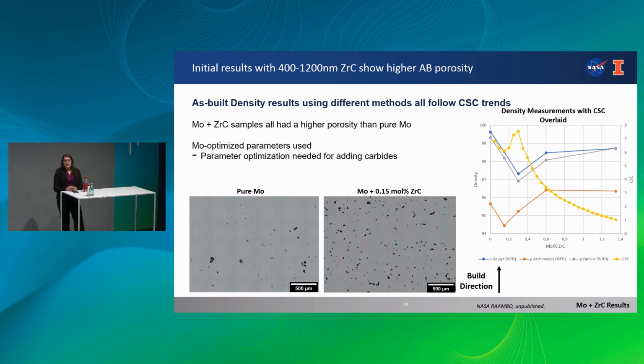One thing to note is that we used all of the moly optimized parameters, and because we've got these nanoparticles added to the molybdenum powder, this is actually going to reduce our laser absorption, so we need to do some parameter optimization for adding these nanoparticles. One of our initial questions was, can we use the same print parameters as pure molybdenum or not? And the answer is no. Additionally, we plan to do some mechanical testing to look at the benefits of these nanoparticles on mechanical properties, if anything.